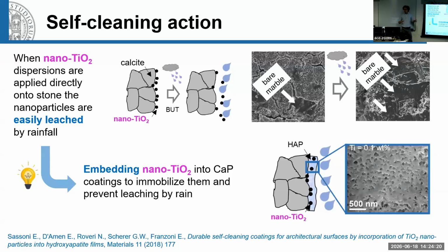This is already known, it's already done since a long time, but the problem is when people apply these nanoparticles, for instance, as dispersions in water directly onto a wall like this one, you obtain this photocatalytic activity, this self-cleaning ability, but the problem is when it rains, especially like today, these nanoparticles are washed away by rain because they are not chemically bonded to the substrate. So what we thought was, okay, we saw that we are able to create protective layers on the surface. Let's try to use them to immobilize the nanotitania nanoparticles onto the surface. So you see here, the idea was forming a protective layer, embedding the nanoparticles so as to obtain a durable, long-lasting